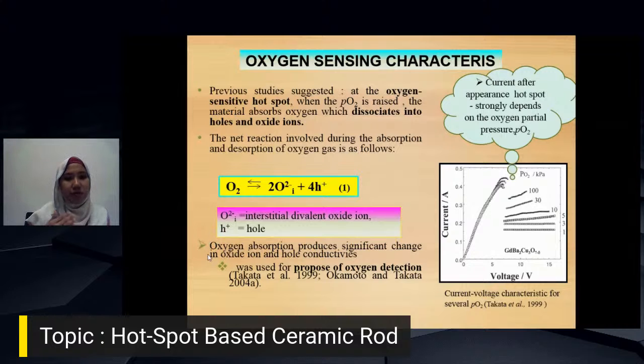Oxygen absorption produces a significant change in the oxide ion and also the hole conductivity, which is used for the purpose of oxygen detection. If you refer to this figure, the output current after the appearance of the hotspot clearly and strongly depends on the oxygen partial pressure. That is quite good when talking about the oxygen sensing characteristic. Without external heating, it can work as an oxygen sensor, which is self-heating. Here you can see that after the appearance of the hotspot, when you change the oxygen partial pressure, the output current is also different. It depends on the concentration of oxygen in the surroundings.